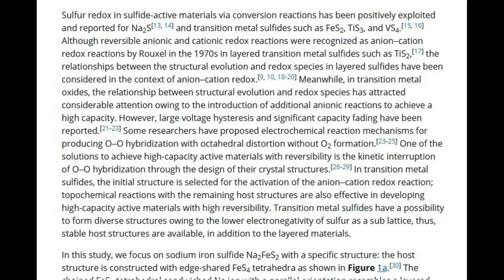Sulfur redox in sulfide active materials via conversion reactions has been positively exploited and reported for Na2S13,14 and transition metal sulfides such as FeS2, TiS3, and VS4.15,16 Although reversible anionic and cationic redox reactions were recognized as anion-cation redox reactions by Rouxel in the 1970s in layered transition metal sulfides such as TiS2,17 the relationships between the structural evolution and redox species in layered sulfides have been considered in the context of anion-cation redox.9,10,18-20